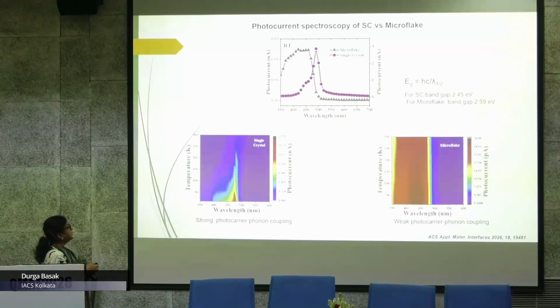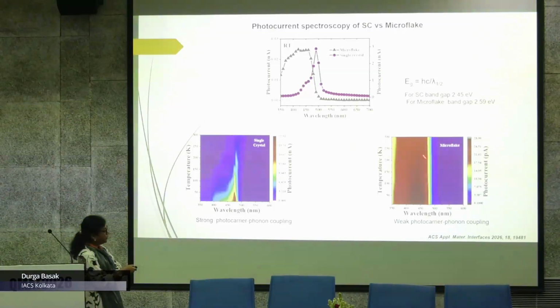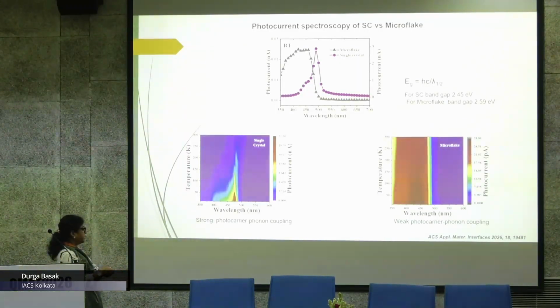So we have studied this experiment at different temperatures, and this is the contour plot, which says that as we decrease the temperature, we get a sharp peak, but there is always a shoulder in the range of 500 to 400. But in case of microflakes, we get a sharp peak, and there is no change in the photocurrent. So we say weaker photocarrier-phonon coupling happens here, whereas strong photocarrier-phonon coupling happens in case of single crystal.